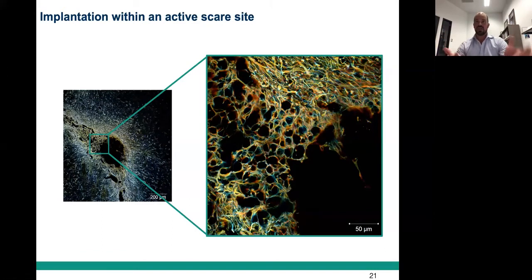So the real take-home message here is that we can actually switch the inflammatory state from this aggressive, cytotoxic, reactive event that's occurring, we can actually switch these cells to a cytotrophic state even within an active scar site, despite all the biomolecules that have been secreted.